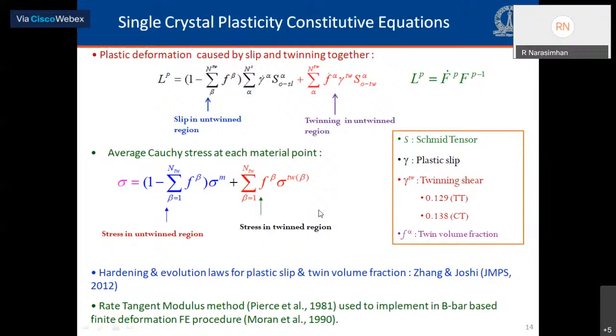In our calculations, we made use of the hardening and evolution laws for plastic slip and twinning. These are phenomenological laws given by Zhang and Joshi. And one of the hallmarks of their work was they actually benchmarked these parameters against channel die compression experiments of Hosford and Kelly corresponding to 6 or 7 orientations for magnesium single crystals and tuned their material parameters. So we used all those values in our models, in our analysis as well.